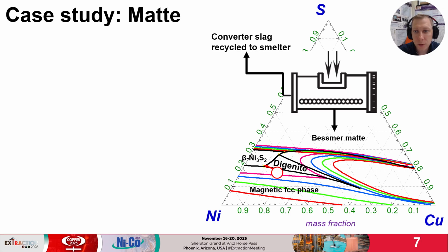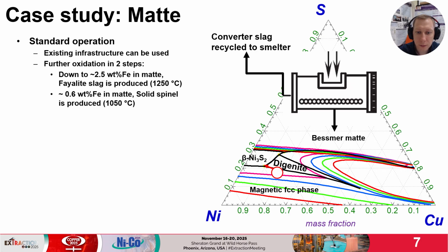The matte produced during the smelting and settling in electric furnace still contains iron. It is removed through oxidation, typically in Peirce-Smith converter. This is done in two steps, bringing the concentration of iron to 0.6 weight percent. The resulting product, often called Bessemer matte, belongs to the copper-nickel sulfur system with impurities.